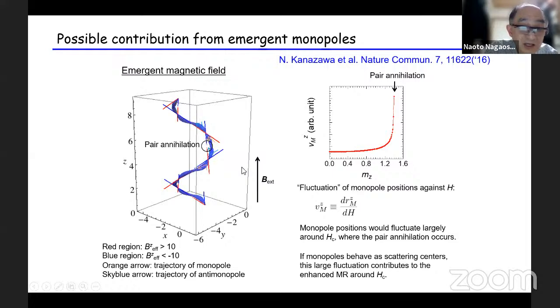So then eventually this monopole and anti-monopole will annihilate in pairs. So this is the annihilation point of a monopole and anti-monopole as a function of the magnetic field of a uniform magnetization. So around this critical point, a very small value of a magnetic field will change the distance between the monopole positions. So this is a sort of critical phenomenon. And because beyond this point, you don't have any monopole or anti-monopole, that's why we regard this as a topological phase transition driven by the external magnetic field.